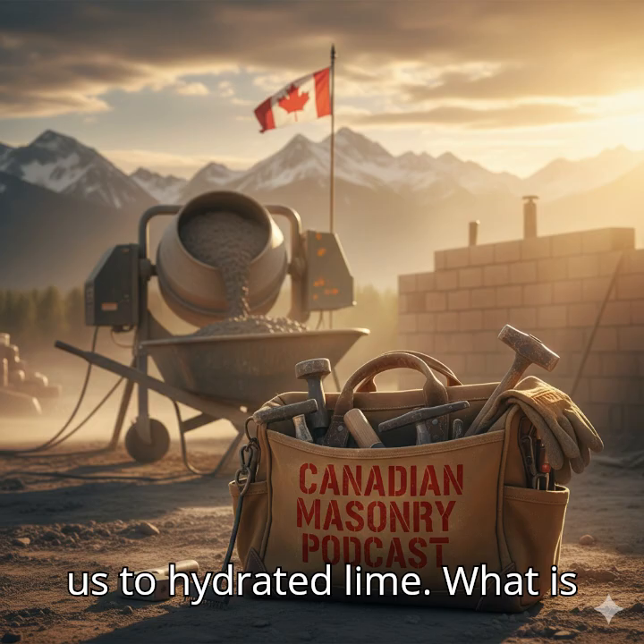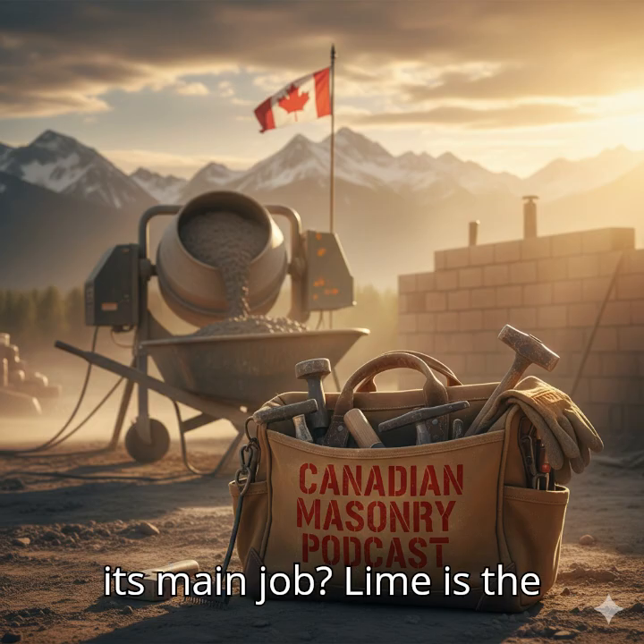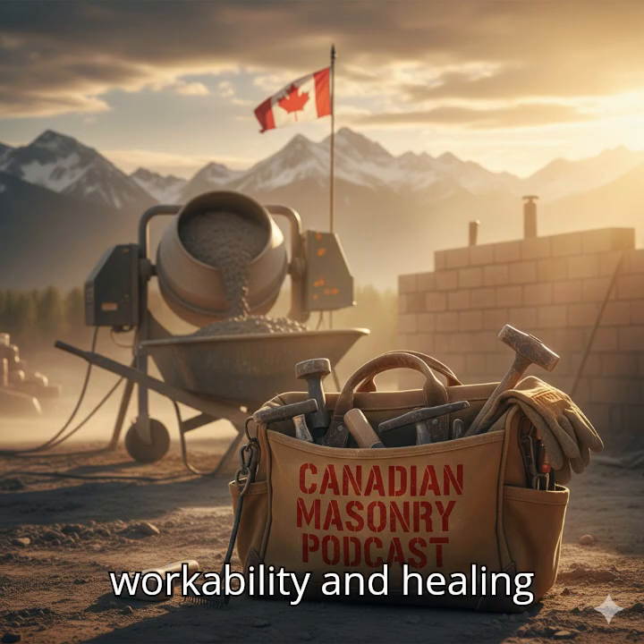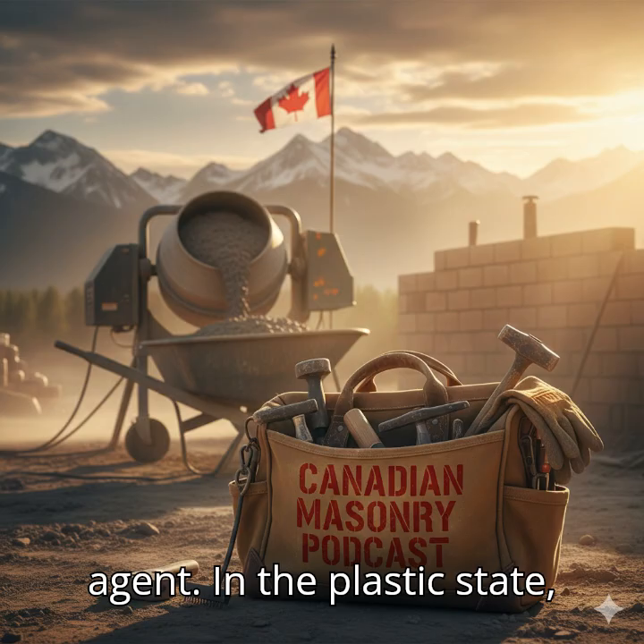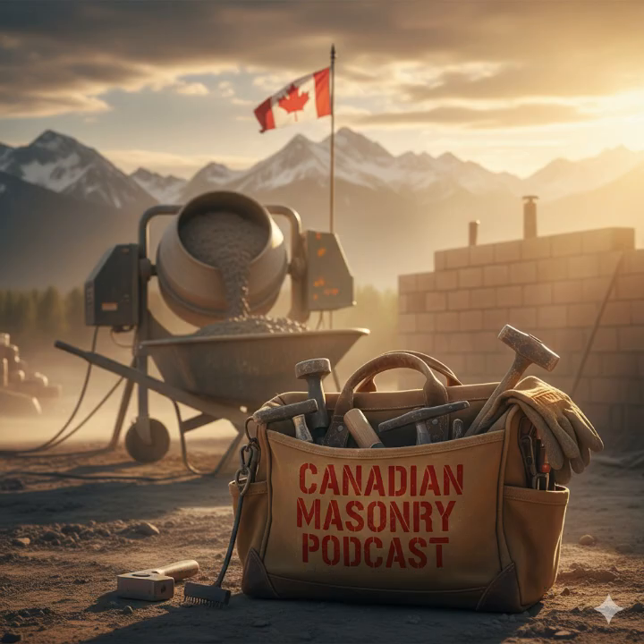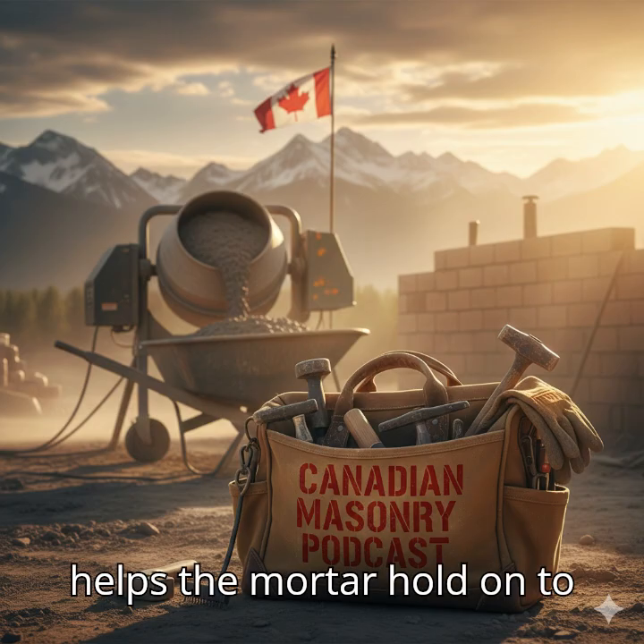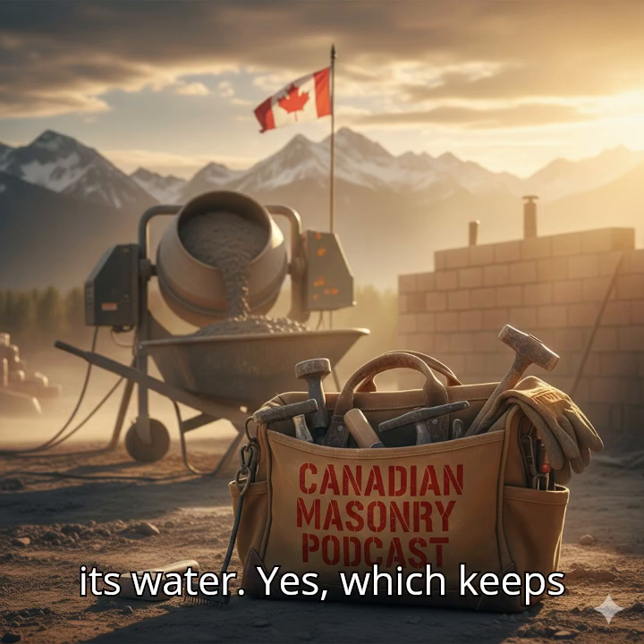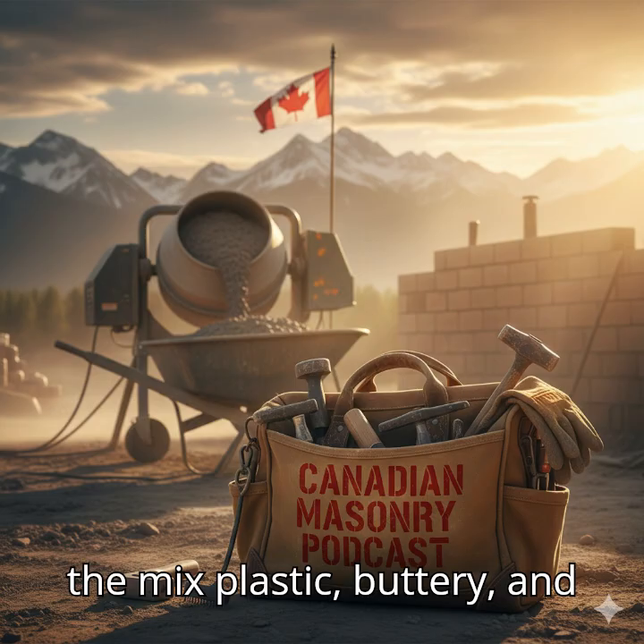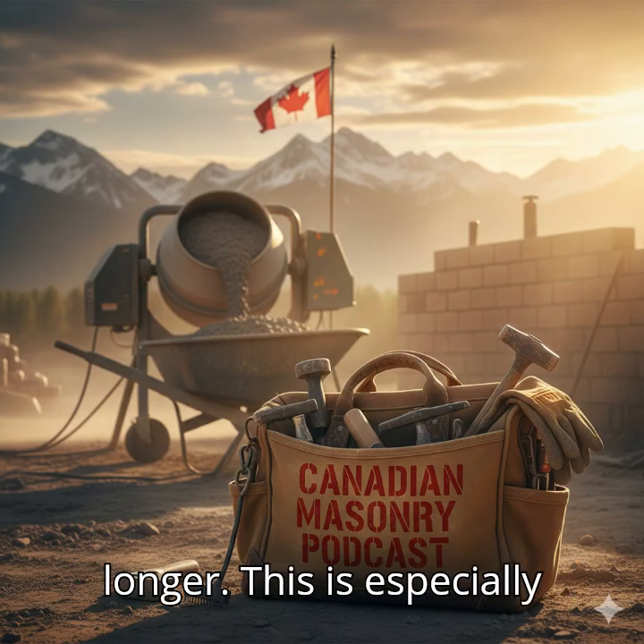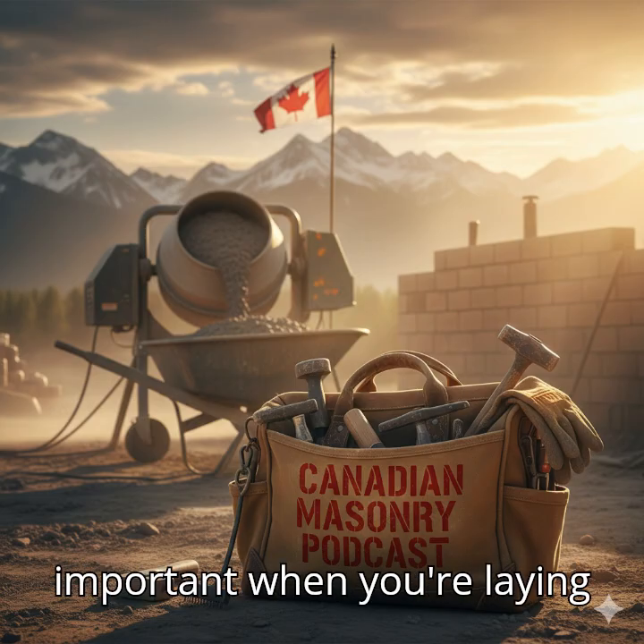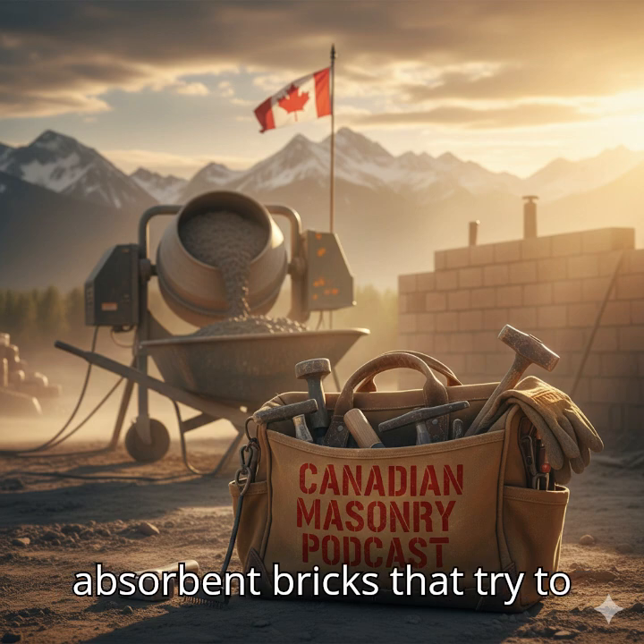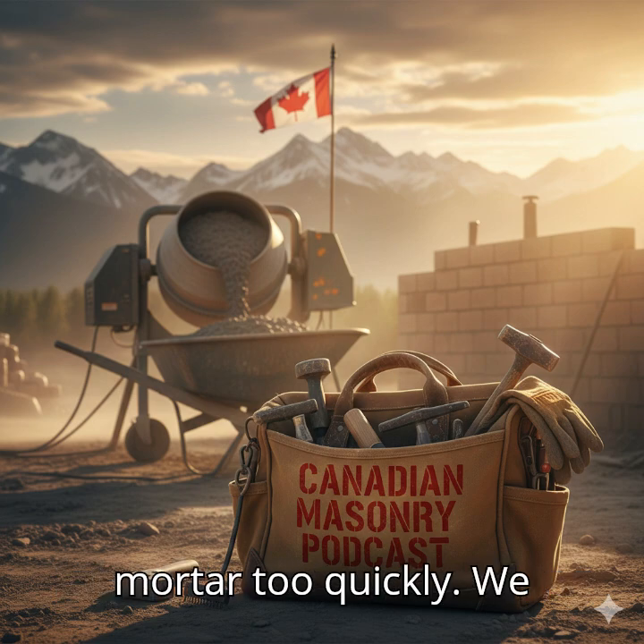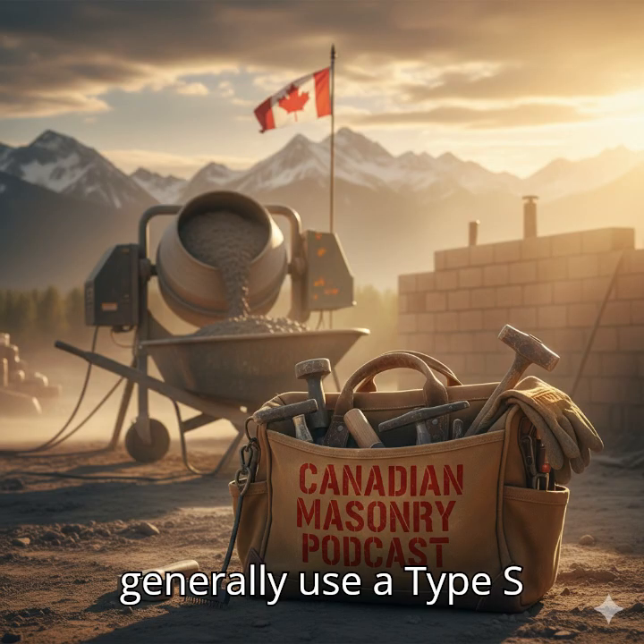And that brings us to hydrated lime. What is its main job? Lime is the workability and healing agent. In the plastic state, it's a mason's best friend. It dramatically increases water retentivity. So it helps the mortar hold on to its water. Yes, which keeps the mix plastic, buttery, and easy to spread for a lot longer. This is especially important when you're laying absorbent bricks that try to suck the water out of the mortar too quickly. We generally use a Type S hydrated lime.